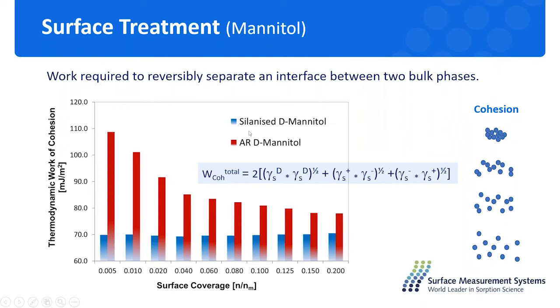So here, from the previous result, we calculate that the silanized D-mannitol is hardly changing as a function of coverage and also has a lower work of cohesion compared to the untreated mannitol, which is the red bar here, which is changing as a function of coverage and also very high in the work of cohesion. So what we can predict here is that the untreated mannitol will have a higher tendency to aggregate compared to the blue bar, the silanized mannitol.